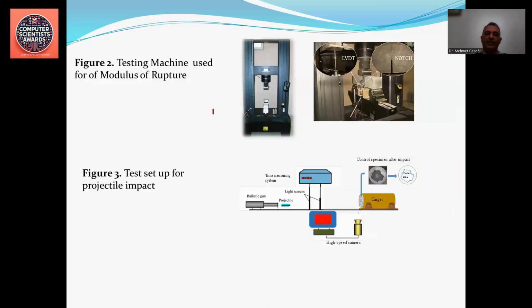The testing of the concrete mixtures in the hardened state was performed by means of an Instron machine with a capacity of 250 kilonewton, and the 3-point bending and fracture tests were conducted by means of closed loop operation. This test setup shows the projectile penetration test.